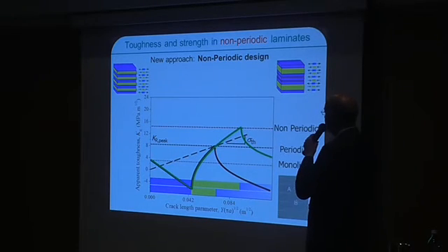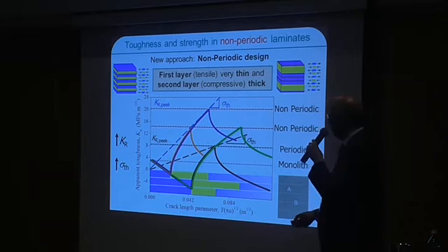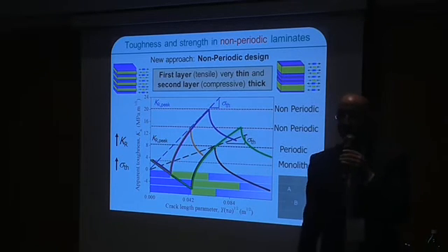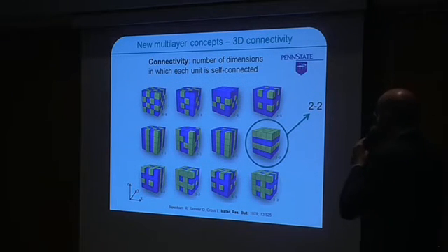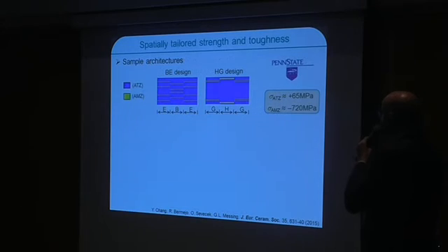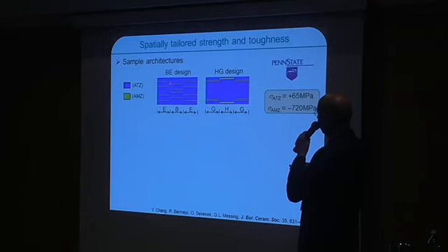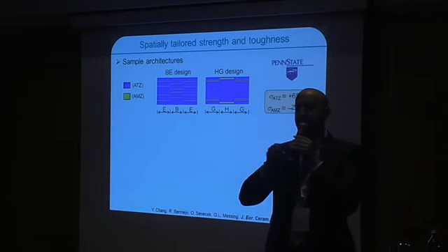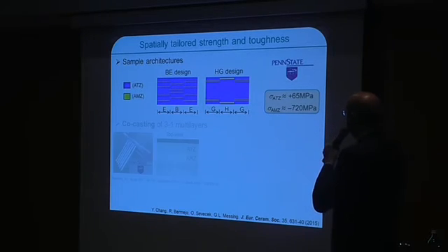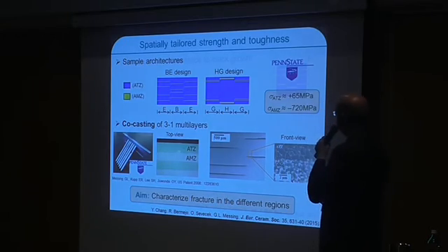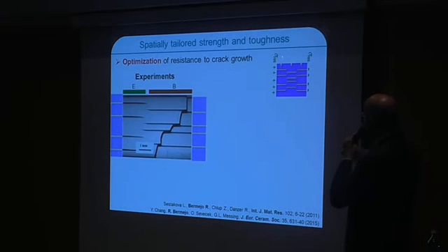Using this simple model, we can predict relatively high values for these ceramic laminates. These are the models, and then we were thinking of using some experiments for that. We'll not go into detail, but we fabricated some structures where you can have, within one single sample, different regions where the layers are disposed in different locations. And it looks like this. So using this model, you can see we put some cracks or some notches there. And then we did the bending test.